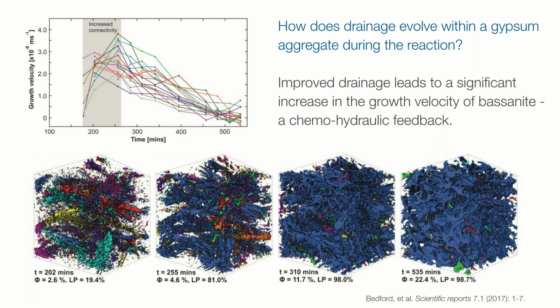This interconnection allows the sample to drain the pore fluid pressure, which was shown previously, to feed back on the reaction advance. And in that time interval, we also see a very significant growth spurt in the growth of individual gypsum grains, hemihydrate grains, as we see that here, right? And then we can follow the consolidation of that porosity.